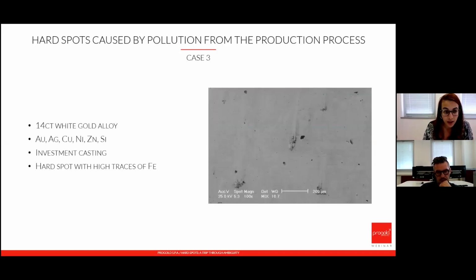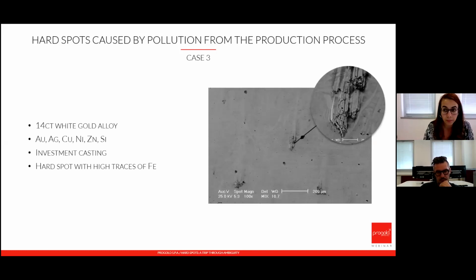A third case that we can have is also a contamination from iron. It is very common when we use continuous casting that the bar is made out of iron, and if we don't eliminate the part that comes in contact, we have many diffusive mechanisms that take place at very elevated temperatures, such as the ones of casting, and this contamination of iron was actually coming out of it. So we have to be very careful where our metal has been and what elements it has been in contact with in order to determine the possible pollutants that we can have.